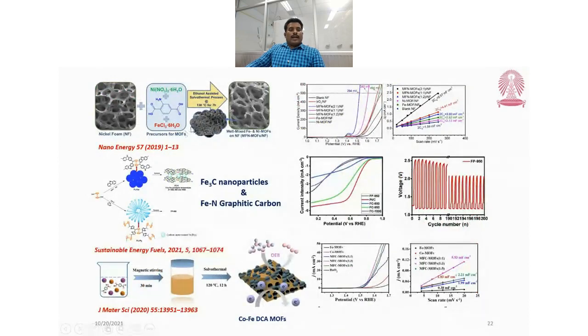This is another similar example of a synergetic effect, where two different MOFs are directly grown on nickel foam and evaluated for OER performance. It gives a better performance, as well as the iron nanoparticles mixed with nitrogen-doped graphitic carbon. It gives a better ORR performance, as well as better durability in the battery testing. Another one, cobalt and iron MOFs, can be mixed together and evaluated for the OER performance.